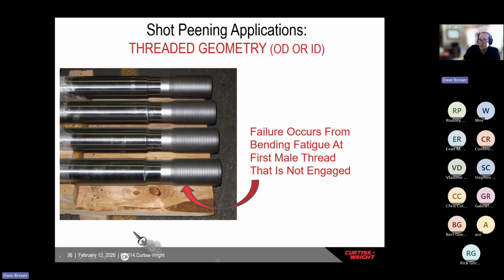Another are threads, in this example male threads. Whenever you shot peen these, it'll generally be a lower energy shot peen, either with glass beads or small steel. The main goal is to get complete coverage on the thread area without destroying the thread profile. But threads tend to be pretty notch sensitive, and typically on a male thread, the top part acts as kind of a lever to go back and forth, while the engagement disengagement thread is where most of the stresses occur, and usually where the fatigue failure will happen.